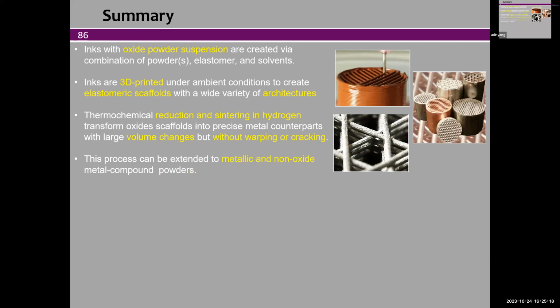This is shown here. This can be extended to metallic or even non-oxide powders. I didn't show this, but we can also print with hydride, for instance, and then decompose the hydride. That's a very good option for titanium. Print titanium hydride, decompose, and form titanium that sinters.